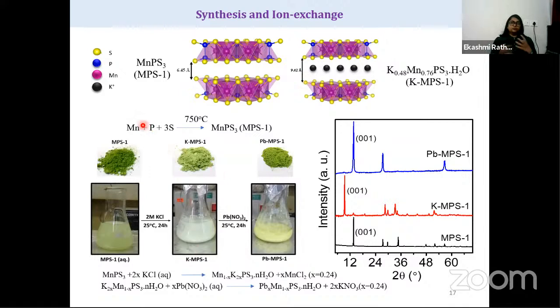Now, how do we make this compound in our laboratory? We take stoichiometric amounts of manganese, phosphorus, and sulfur powder, and grind them in a pestle and mortar. Then we seal the tube reaction and conduct it in vacuum. The vacuum pressure is around 10 to the power of minus 4 torr, and we keep the sealed tube at 750 degrees Celsius for 7 days, and it gives rise to a beautiful green compound. When we treat it with potassium chloride, its color changes to light green.